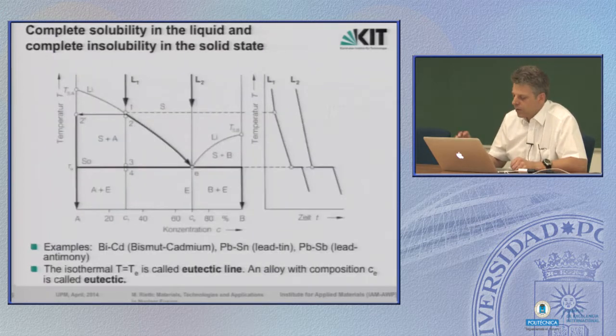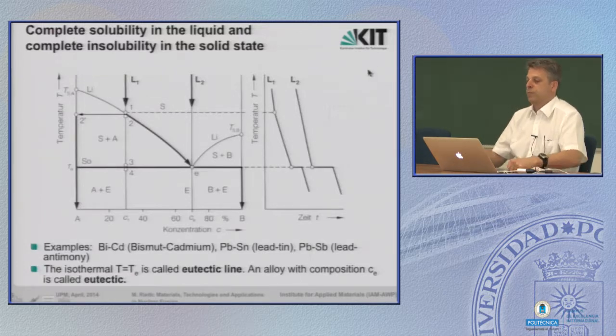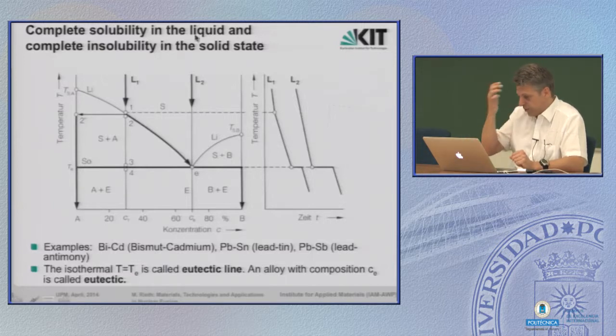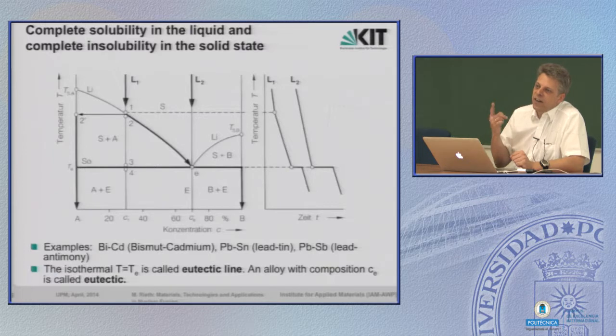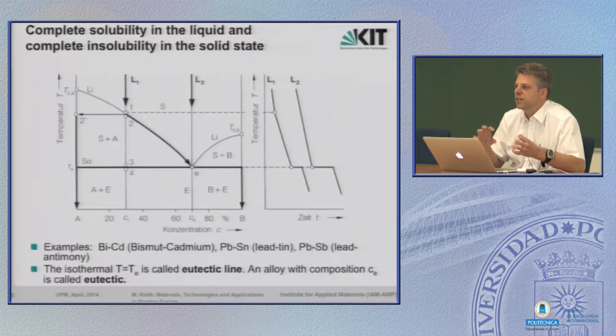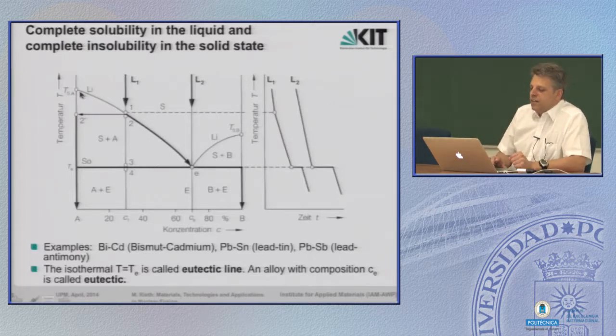That's one of the several possibilities we face. Another one is if you mix two different kinds of elements, they can show you a complete solubility only in the liquid phase, but in the solid state, they are completely insoluble. This means they don't mix in the solid state. In this case, the phase diagram looks like that.